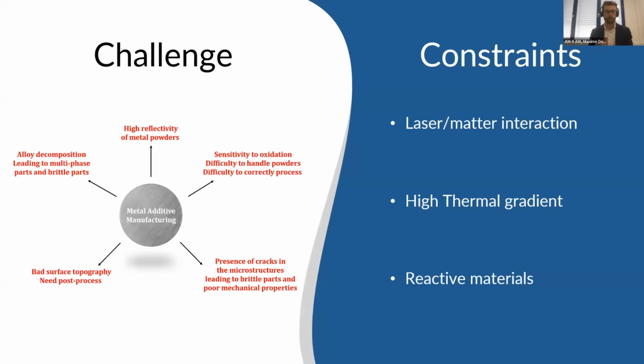So let's have a brief reminder about the challenges metal additive manufacturing is facing in terms of material. We could have some difficulties like reflectivity of metal powders, sensitivity to oxidation, difficult to handle powders, presence of cracks in the microstructure due to hot cracking phenomenon, bad surface topography, and also alloy decomposition due to high laser power. Basically, these challenges come from the constraints that laser-based metal additive manufacturing applies. So we can cite laser matter interaction, high thermal gradient, and reactive materials.